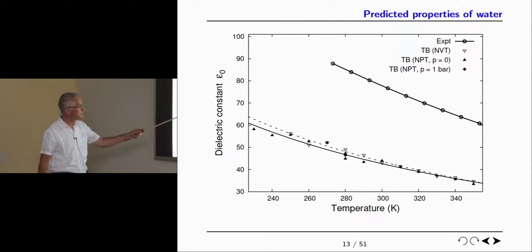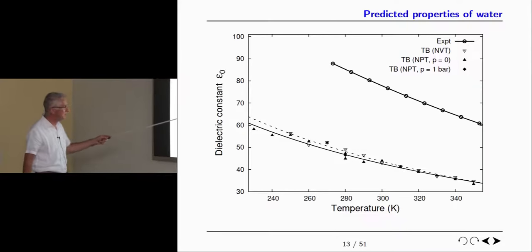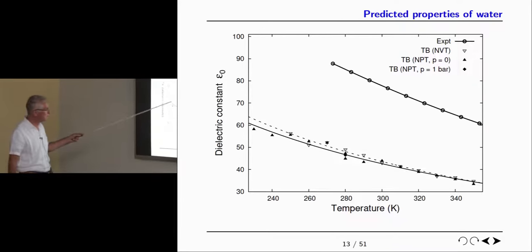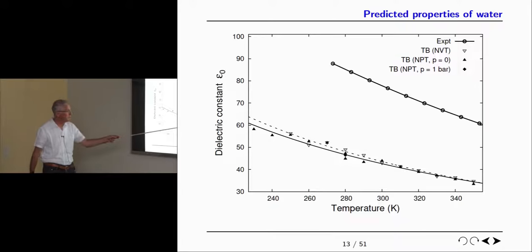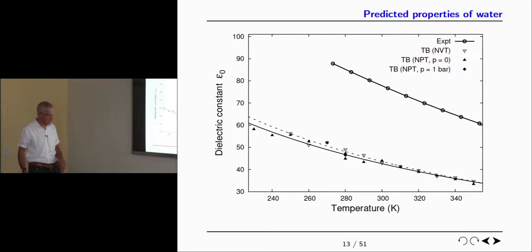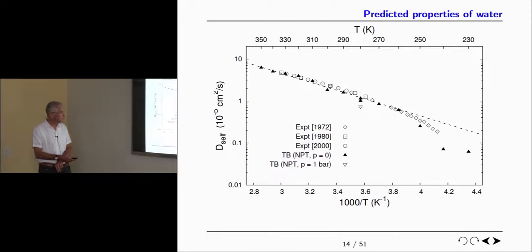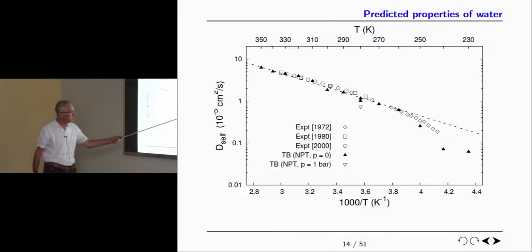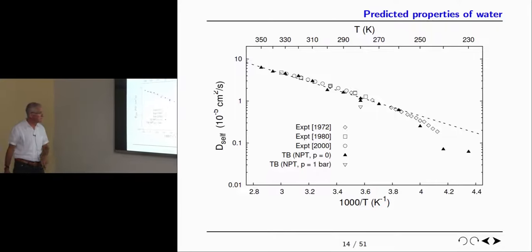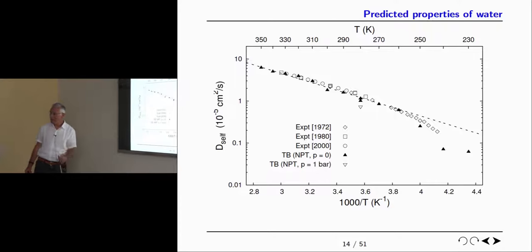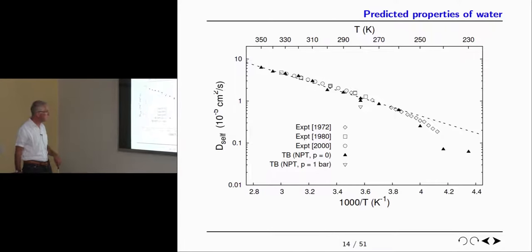So the experimental dielectric constant is here as a function of temperature, and these are our values. So we get the trends in the temperature dependence right, but we will have to do some more work if we really wanted to have a model of water with the correct dielectric constant. But what does come out incredibly well, and this was very gratifying, is the self-diffusivity, the self-diffusion coefficient of water as a function of temperature. So these are our calculations, these black triangles, and they are compared with experimental data. So that's extremely gratifying that none of this is fitted now, you see. We're only really fitting in the early stages. So everything I'm going to show you now are basically predictions of the model to show how good it is.